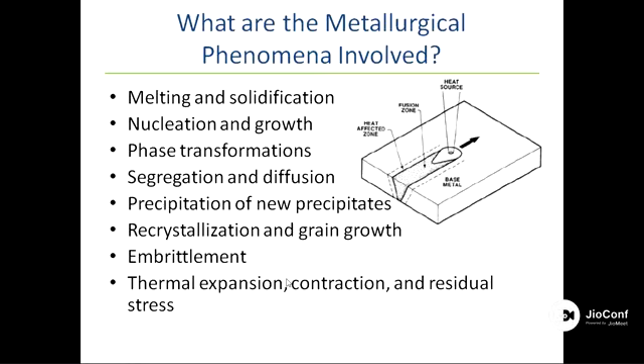So this kind of structure, if it is not cross weld heat treated, right? In automobile structures, like dual phase steel, or steel like high strength low alloy steel, HSLA steel, if they are not given proper treatment, they may be subjected to embrittlement, because many hard phases are present, like martensite and bainite. The martensite has to be tempered by means of post-weld treatment.